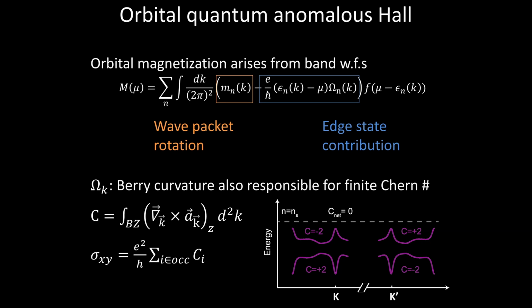Now, this raises an interesting question because the nature of the magnetism in these systems in general is mostly orbital. It comes from the fact that the electronic wave functions have essentially equilibrium currents in the plane. The spin plays actually a relatively negligible role. So these are orbital magnets. Okay. And there's a theory for orbital magnetism, at least for non-interacting electrons, which is roughly applicable. You can think about this as, for the occupied states, what's the projection of the angular momentum operator if you think through the physics of the Bloch wave functions, okay? And people usually talk about two contributions to this. There's some part that comes from wave packet self-rotation, and then there's a part that comes from center of mass motion, if you want to think about wave packets propagating in a solid.